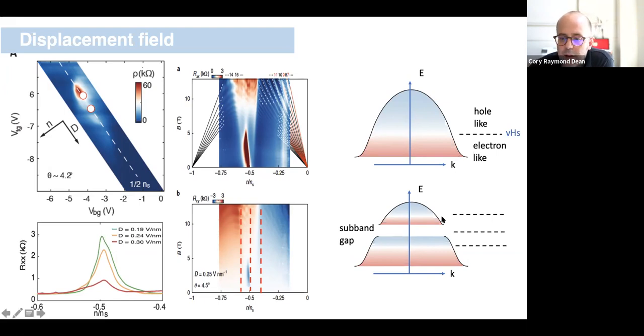So I now have something like a Van Hove singularity emerging right before the gap appears. I would transition in sign around the gap, and then I would see another transition at some higher doping. And the only thing I'm trying to identify here is that really, if there's no subband gap, I expect there to be a single Van Hove-like characteristic signature in the Hall resistance. And if I open a subgap, I expect there to be 2 more inflection points in the sign of the Hall resistance.